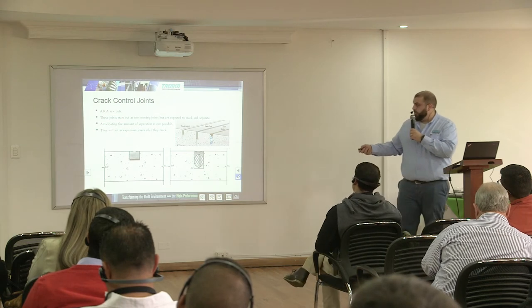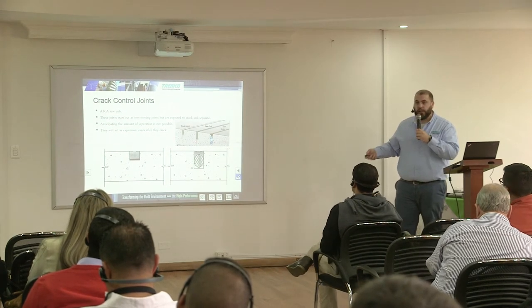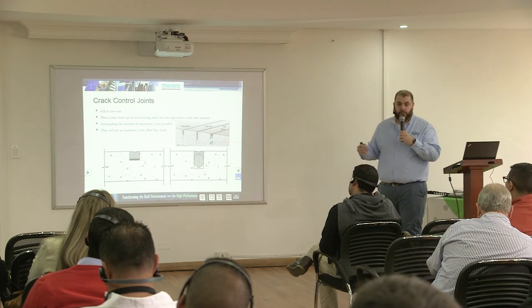The point is, if you don't treat that joint and you have a crack get down in there, you have moisture get down in that crack, moisture will rust the rebar, and the oxidation force of the rebar is greater than the internal strength of the concrete, typically. So what you'll have happen is you'll have concrete spalling, you'll have concrete popping off, and that's a much more expensive fix than installing sealant in the first place and performing typical maintenance on the sealant.